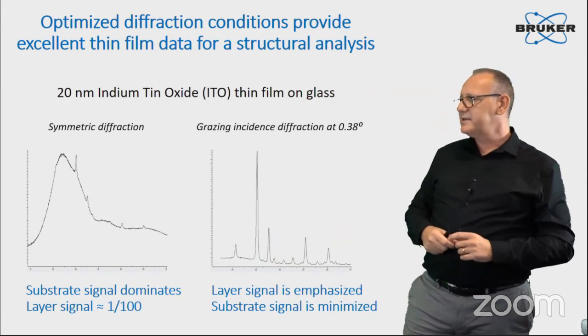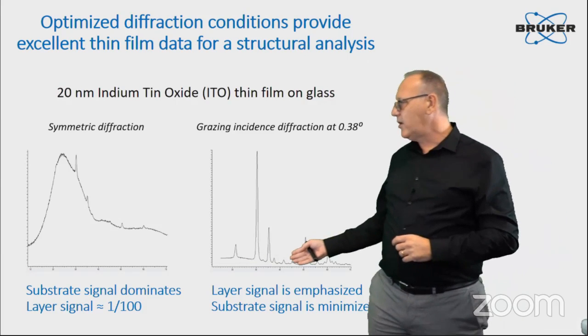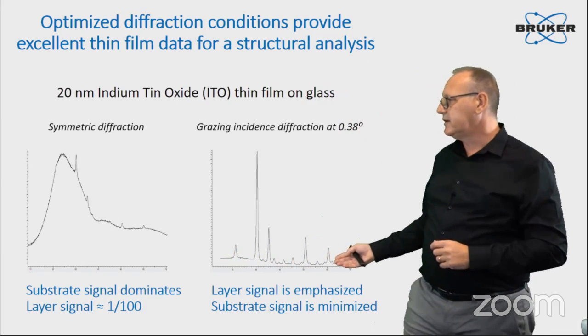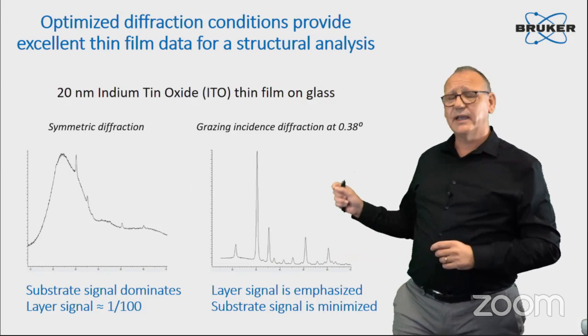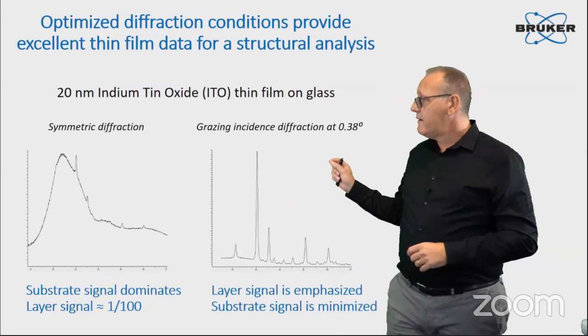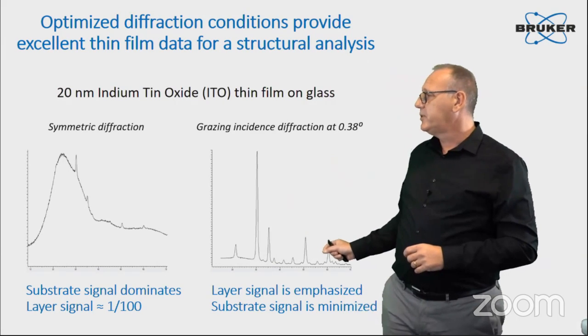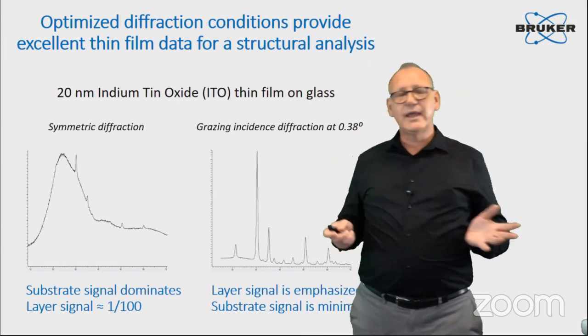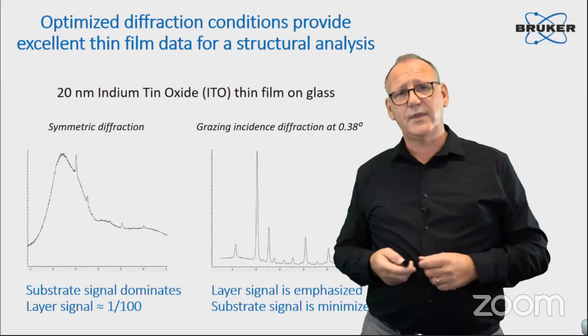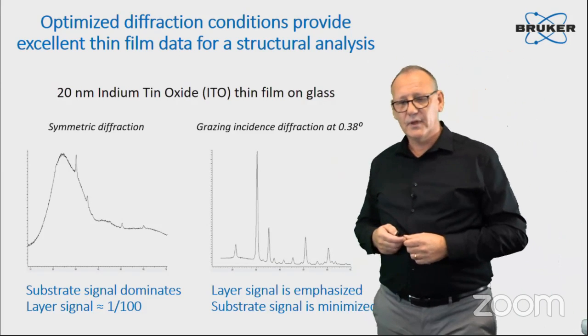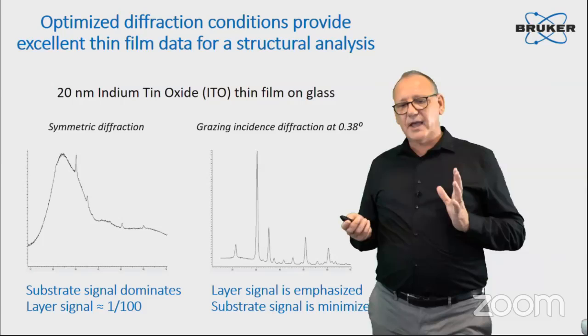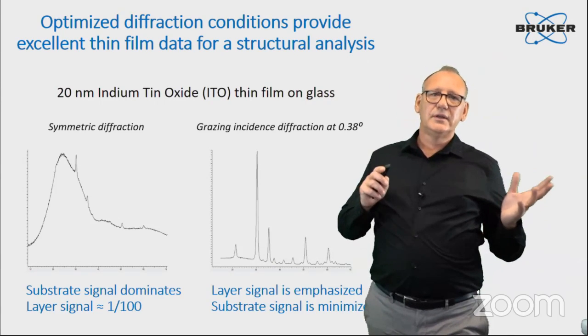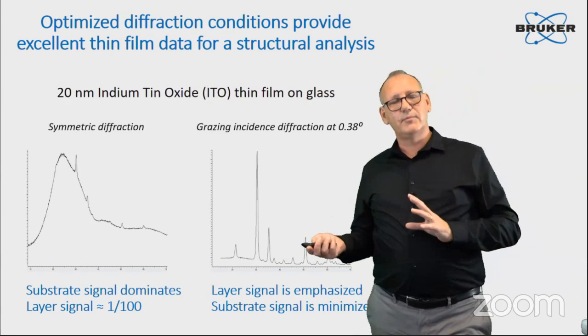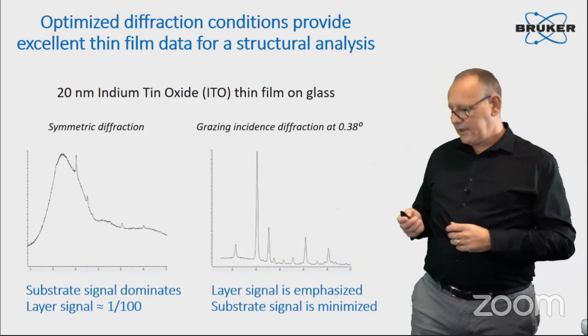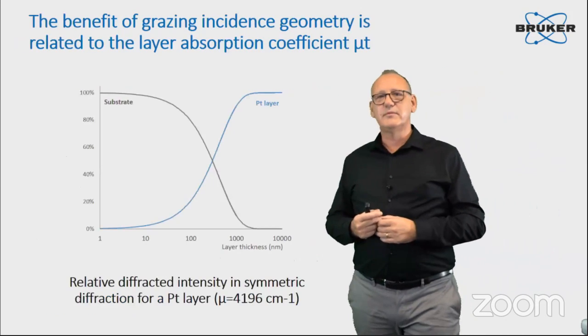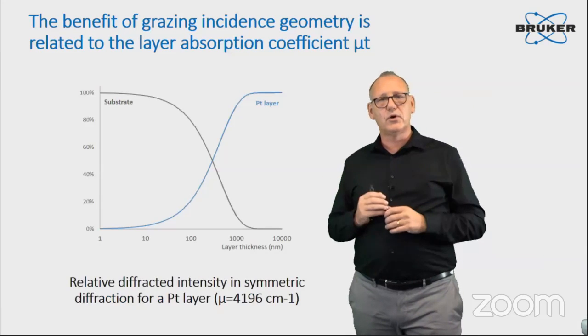We have emphasized the layer signal, and we have basically almost vanished the substrate signal. And those data have good enough quality, very smooth peak shape, pretty large angular range. So we can think of doing some structural analysis on this sample. The question is also sometimes how to know if I have to set up GID or if I can still do some locked coupled or some symmetric scan. Again, the mu-t coefficient helps you here to understand where to go.